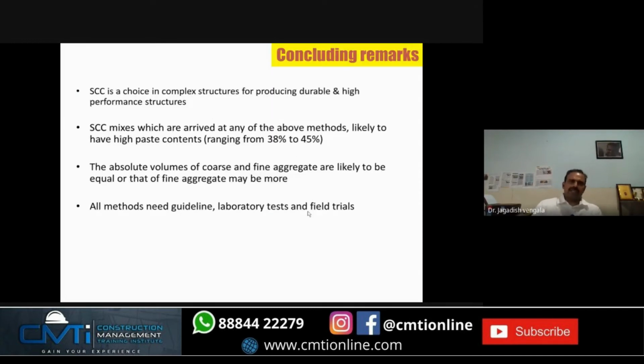Finally, coming to the end of my presentation, it's definitely a choice for complex structures, and for SCC you have to arrive at the mix with any of the methods. But paste content is very important. You're likely to have 38 to 45% paste content. Coarse and fine aggregate are either equal or sometimes coarse aggregate is lower, and all methods need guidelines, laboratory tests, and field trials. Very important. You can't just go and cast it on site.